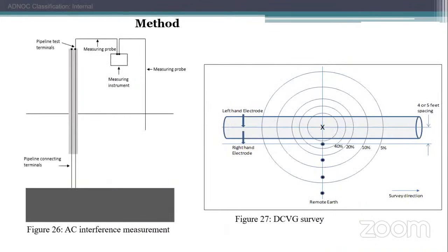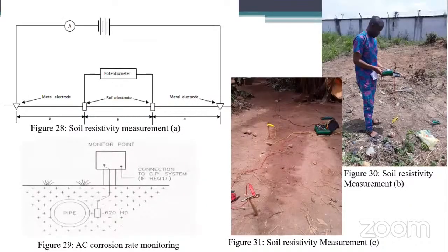So this is just a schematic. Figure 26 shows the pattern in which the AC voltage was measured, how much AC voltage was introduced in these pipelines. Then the DCVG is to check if the pipeline itself has coating defects that will allow this corrosion to happen. This is me doing a soil resistivity test. The fence you see there is a power plant. Figure 28 is the schematic of the soil resistivity test measuring. Figure 29 is how the resistance probe works.